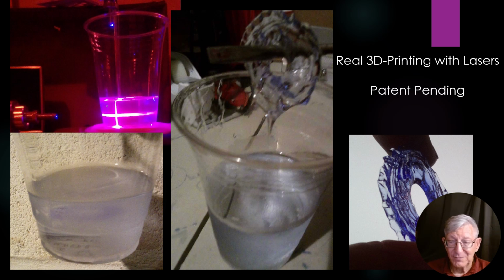And so what you see, which was actually partially obscured by me in this cameo slot, is the part. You'll notice it's hard, it's clean, it's dry, and it's rigid, and that we were able to do that literally in a few seconds. This did not take long to do, and we did it with the two lasers that were overlapping, and maximized the energy density within the resin. That was the process that we were using. This is where the two lasers came together. We pulled the solid out, we dried it off, and that's it.